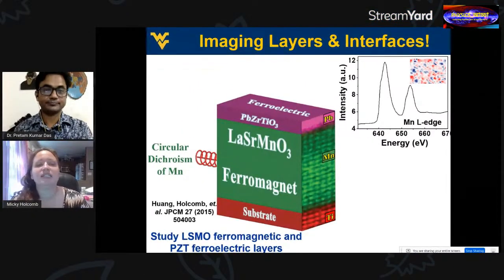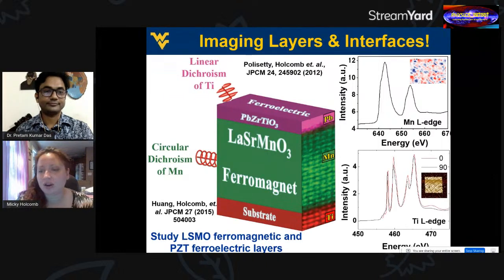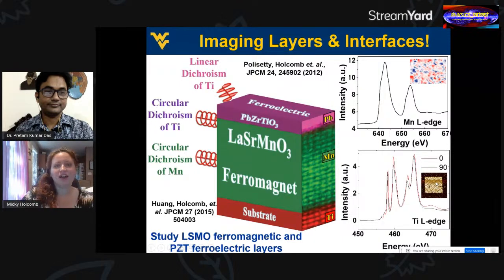So for our magnetic system, we were looking at lanthanum strontium manganite. And for our ferroelectric system, we were looking at lead zirconium titanate. Here we have both the manganese edge, so you can see the magnetic domains, and we also have the ferroelectric domains shown here. And we were able to look at both layers and the interface between them.